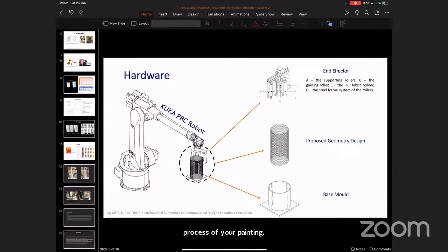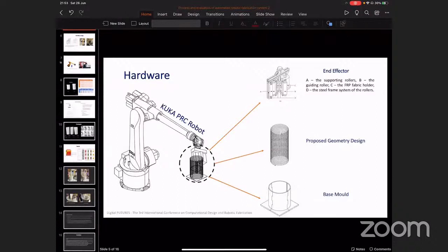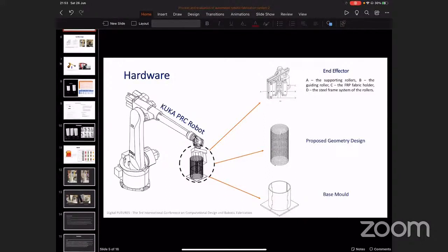Yes. The deviation of the fabrication will depend upon the environment that the formwork is being printed in. And regarding the concrete casting, yes, there is high uncertainty about the hydrostatic pressure the concrete will exert on the formwork. Further research as a next step of this project is about casting concrete on the formed formwork and testing its properties to have a good solid prediction, so that even when it is fabricated, the response to loading is within the prediction limit.